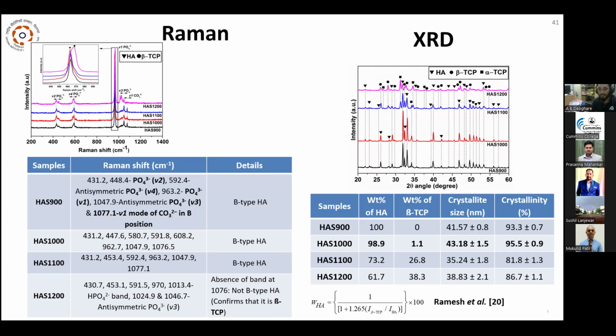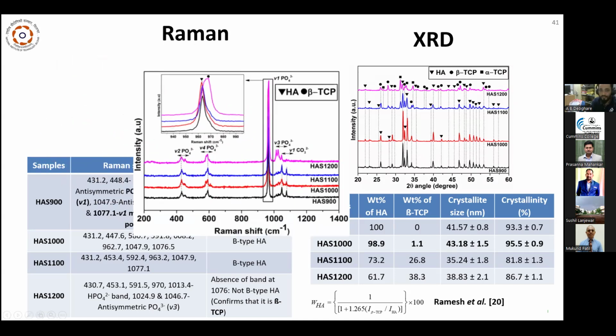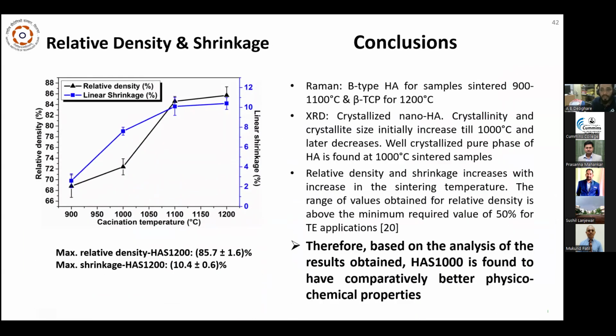Then coming to the XRD part, basically to observe the phase identification and the crystallinity of the prepared sample. It is observed that the prepared samples are well crystalline in nature, as sharp peaks are observed. From the table, it is observed that for the sample sintered at 1000 degrees, the crystallite size is maximum, as well as the crystallinity, which is 95.5. Then relative density and shrinkage tests were also performed.